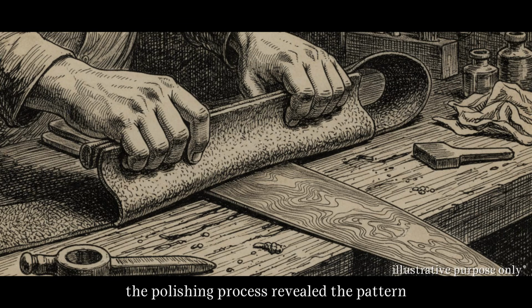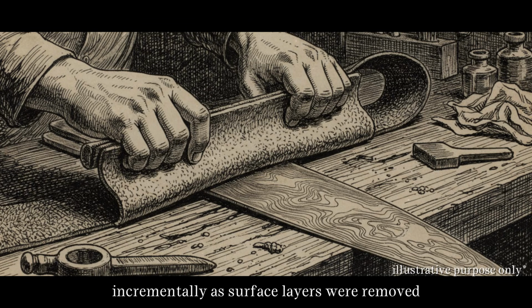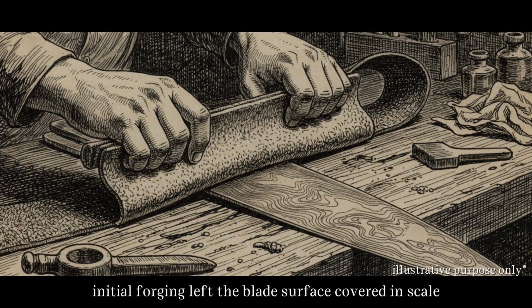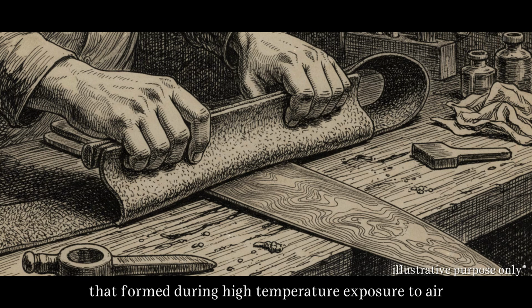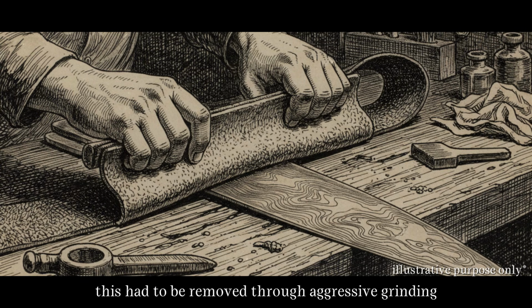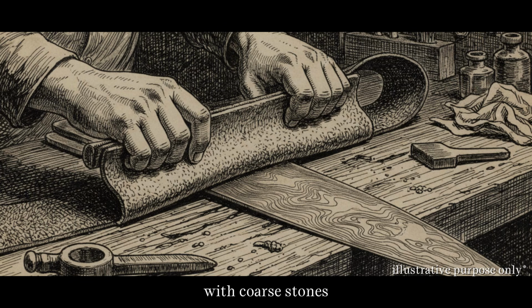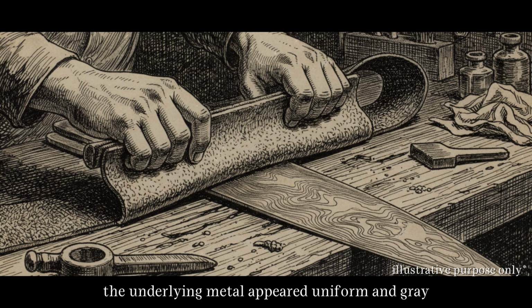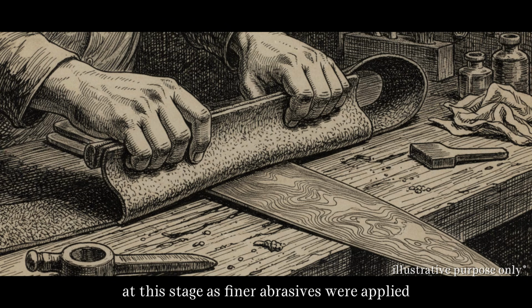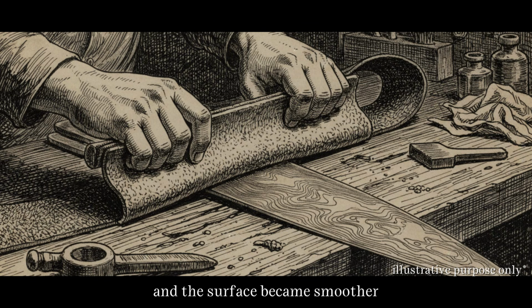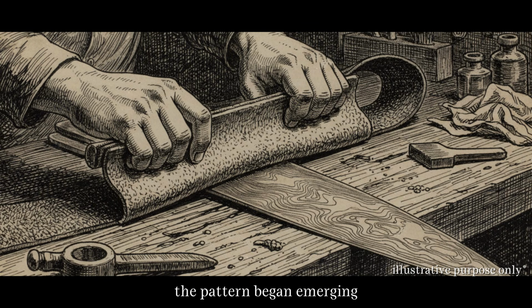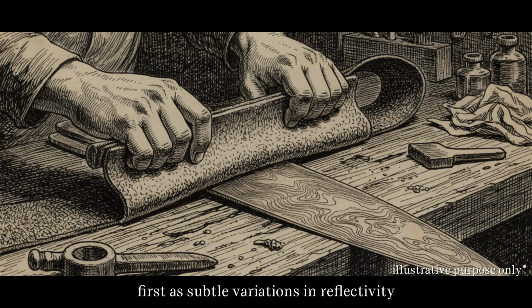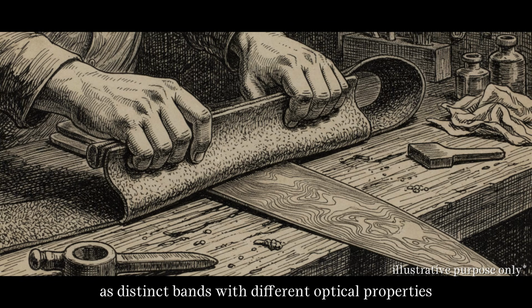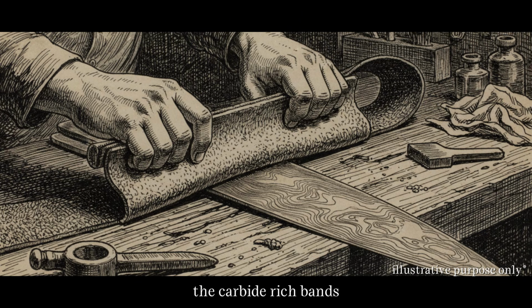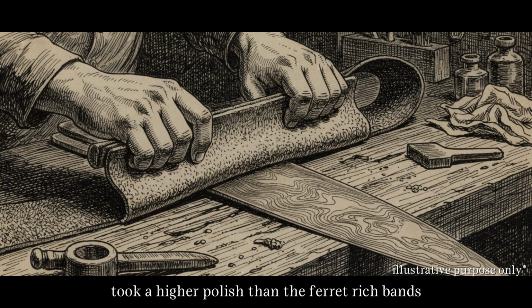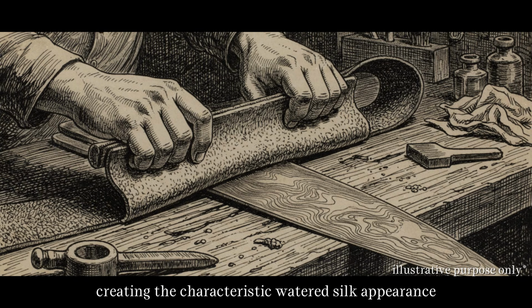The polishing process revealed the pattern incrementally as surface layers were removed. Initial forging left the blade surface covered in scale, oxidized iron that formed during high-temperature exposure to air. This had to be removed through aggressive grinding with coarse stones. The underlying metal appeared uniform and gray at this stage. As finer abrasives were applied and the surface became smoother, the pattern began emerging. First as subtle variations in reflectivity, then as distinct bands with different optical properties. The carbide-rich bands took a higher polish than the ferrite-rich bands, creating the characteristic watered silk appearance.